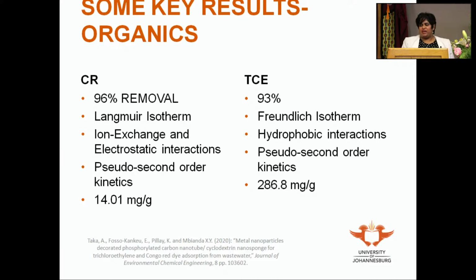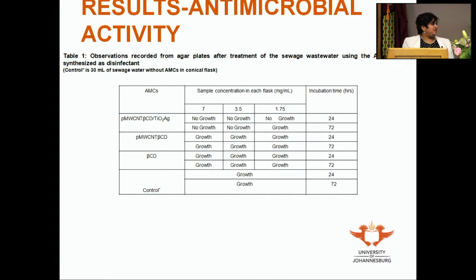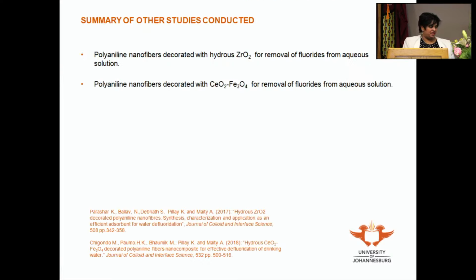Different mechanisms or interactions were involved, but a noteworthy observation was the fact that the adsorption capacity for trichloroethylene was far higher than that of Congo red dye. So it seemed like this adsorbent did work to absorb different categories of pollutants, but it had its own specific adsorbent preference for certain materials. And these are some unpublished results that I'm presenting to you today. What you see from this data is that the full composite material containing titanium oxide and silver was necessary to inhibit microbial growth. And that was a positive sign to say that it can work for antimicrobial activity.